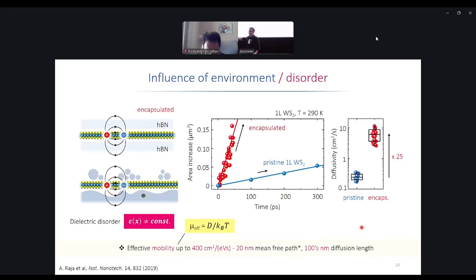So if you measure diffusivity, if you measure free diffusion, you automatically know how the particle will react to an external field. And if some of you are wondering why the electric charge is here, it is because very often in semiconductor physics, we're used to using electronic mobility, which is defined as a drift speed versus voltage, but you can define drift speed versus any type of potential gradient, be it strain or what not, and this will be this quantity. So in this particular case, a diffusivity of 10 corresponds to an effective mobility at room temperature of 400, corresponds to a 20 nanometer mean free path, which is quite a lot, and something like a few hundred nanometers of diffusion length, which is, however, determined by the lifetime of the exciton.